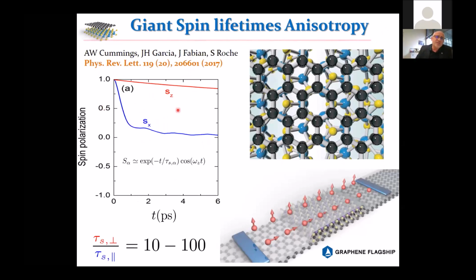giant spin transport anisotropy. So here we just saw all the spin polarization change when you inject a charge with an out-of-plane spin polarization in graphene deposited on TMDs. You see that there will be a very large difference in terms of the relaxation between the in-plane spin injection or the out-of-plane spin injection. And we found that those values could reach several orders of magnitude.